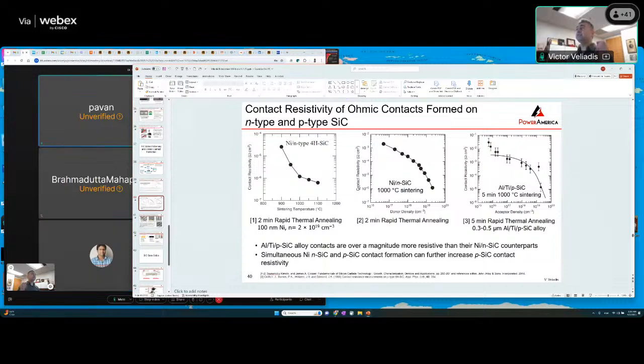So in that case, the best selection would be nickel. By using nickel, you get the optimal contact for the N, and unfortunately it will be a little worse for the P than it would have been with aluminum titanium. So look at this statement: doing simultaneous nickel on N and P for contact formation in a single step has the labor and yield advantage of one photolithography step. Unfortunately, you increase the P contact resistivity versus using aluminum titanium, which would require a separate step. So again, Pawan, it's a trade-off. When I was making devices, and I made devices for many years, the benefit of a single step for N and P was a better choice than doing two separate steps, where I could put aluminum titanium on the P. That was my experience.